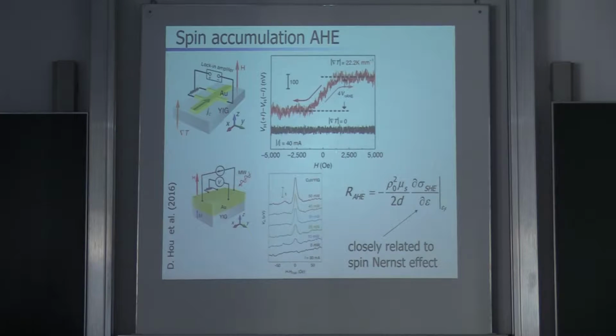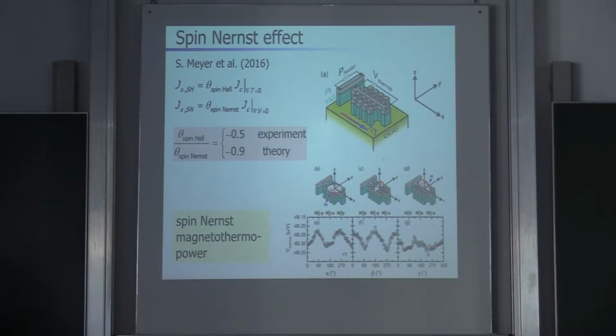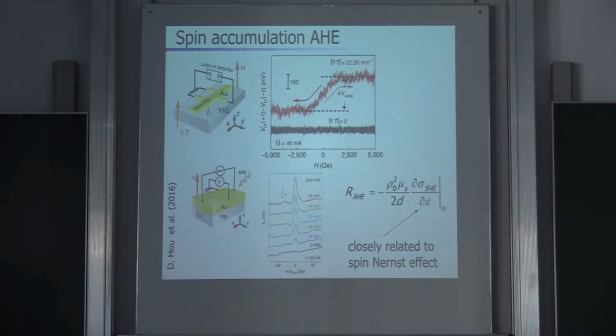If you analyze these experiments, you get a parameter out of it, which looks like this one, this anomalous Hall resistance, which can be written in terms of the spin accumulation μs and the derivative of the spin-Hall conductivity. Now, this derivative of the spin-Hall conductivity is very closely related to something called the spin-Nernst effect. In order to complete the story, let me show some experiments which indeed show that there is a spin-Nernst effect in platinum in this case.